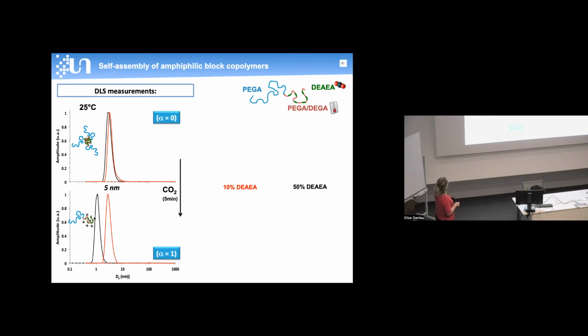Then after 5 minutes of bubbling carbon dioxide, the object here in red, with the lesser amount of carbon dioxide responsive units, the size of the object doesn't change, but with more amine units, the size decreased a bit. We make the hypothesis that at neutral pH, when there are more diethylaminoethyl acrylate units, these acrylates in the neutral form are more hydrophobic, and so the copolymer hardly aggregates, whereas it disassembles completely upon protonation of the units. But this happens only if a lot of units are incorporated.